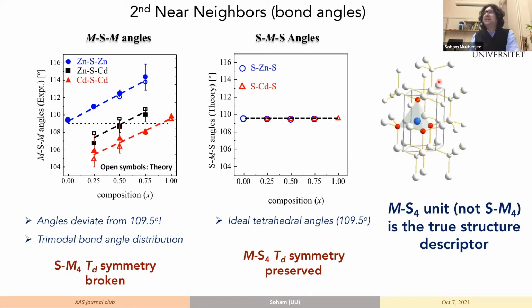So this immediately tells us that to understand the zinc cadmium sulfide hexagonal system, a metal sulfur 4 unit has to be the true structure descriptor of the system. Because if you go to sulfur M4, we can immediately see that the tetrahedral symmetry is broken. And this is because at the M site, we have a mixture of two atoms. So to understand the structure, we have to look at the metal sulfur 4 unit. So what is happening with the angles?